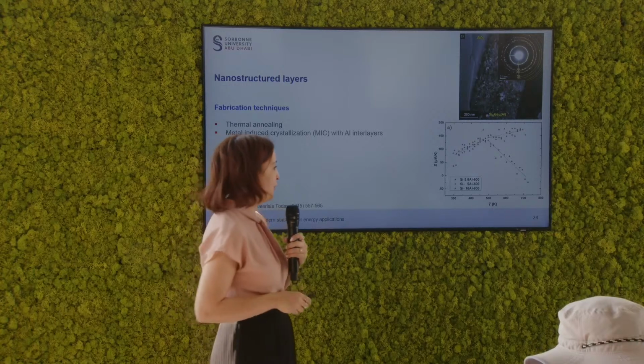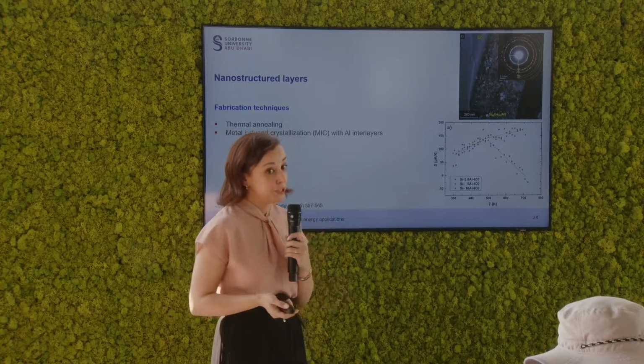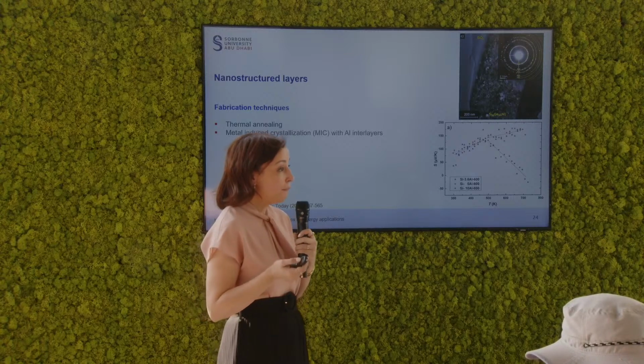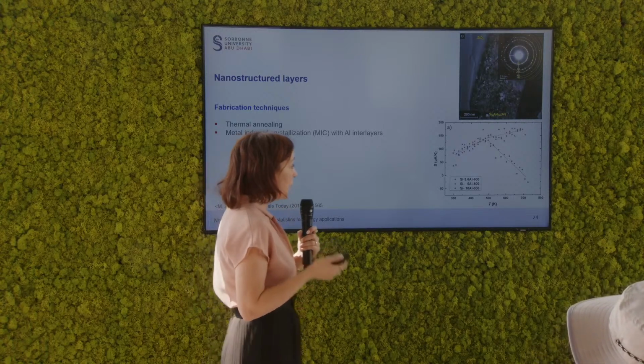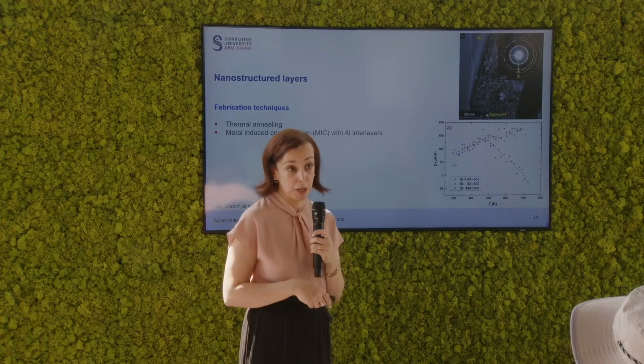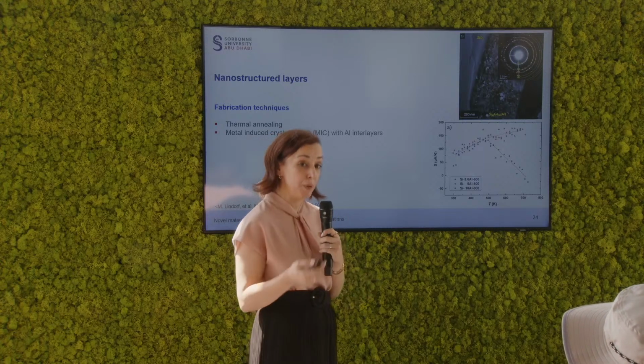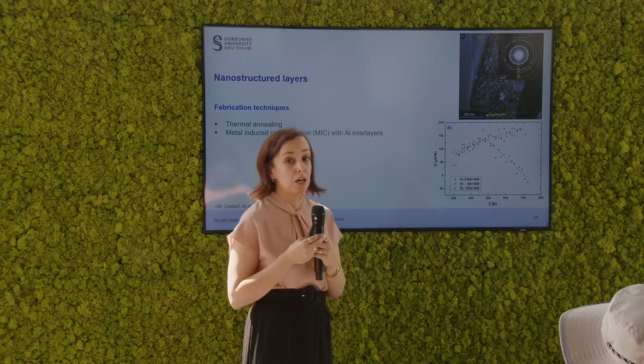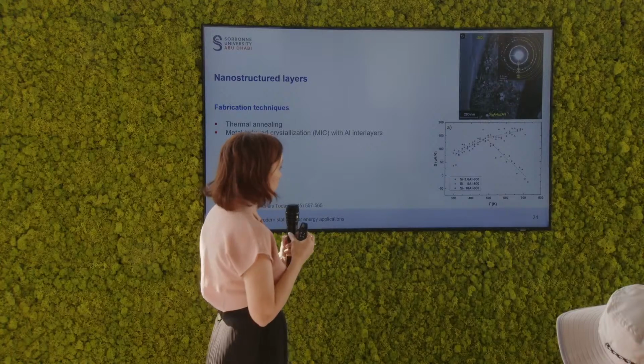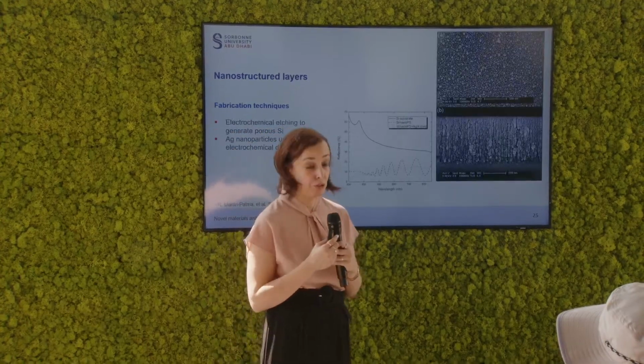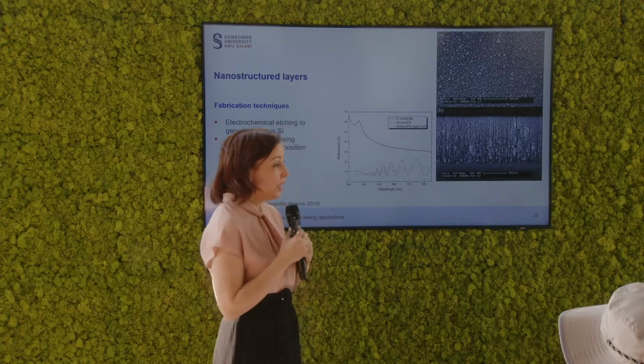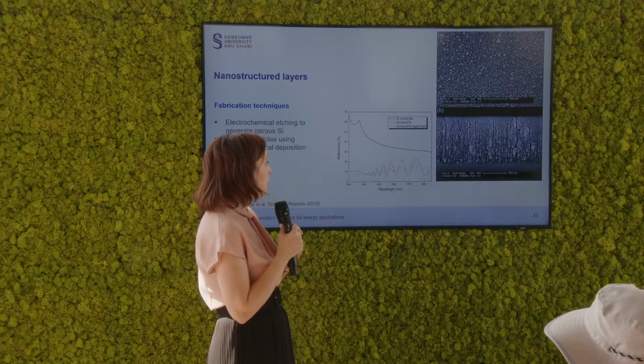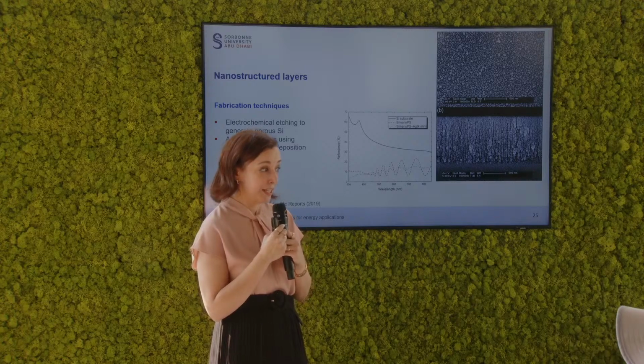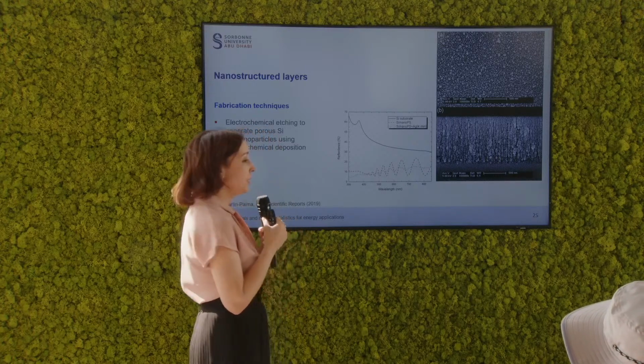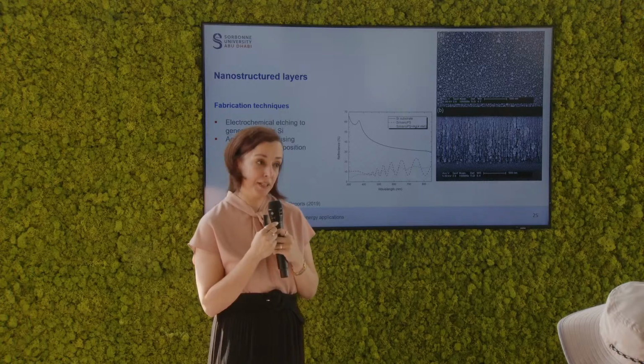Regardless of this minor disadvantage, a Seebeck coefficient in the range of around 150 microvolt per Kelvin can be generated from such a fabrication method. In general, for silicon germanium, your thermoelectric performance can be as high as 250 microvolt per Kelvin. As we are also interested in the optical performance of our device, we can look at another fabrication technique by another research group concerning fabricating nanostructured silicon.